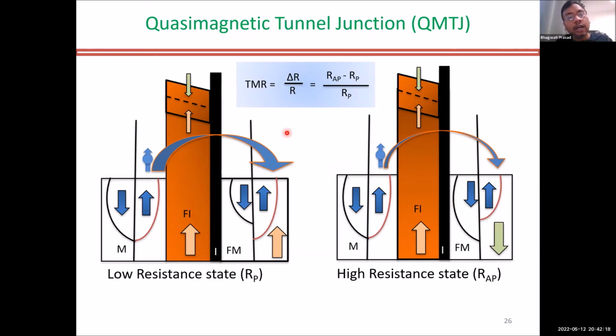The other way of corroborating this fact is when you make a quasi-magnetic tunnel junction. Instead of having two metallic electrodes, now you have one ferromagnetic metal and one normal metal electrode. This ferromagnetic metal will act as a sensor. If your ferromagnetic insulator is giving you a spin filter or spin polarized current, then this ferromagnetic metal will accordingly sense it. That way you can say that this thin barrier is acting as a spin filter. When these two layers are parallel, a lot of current will pass through, and you will have a low resistance state. When these two are anti-parallel, there will be a high resistance state. Then you can calculate the TMR with that.